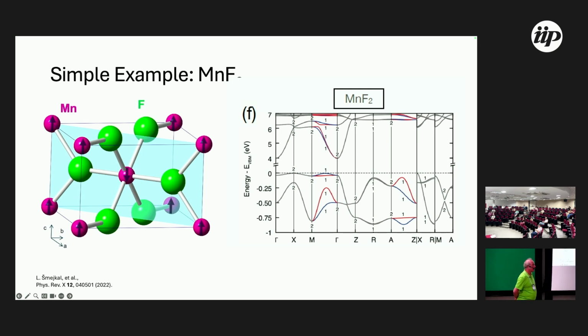That clarifies a lot. So it's basically a canted situation where you have spins oriented in different ways for different sublattices, right? Well, you have two sublattices in this case where they are pointing in opposite directions, but the immediate chemical environment is not the same. So you can tell the two sites apart from each other, just crystallographically already. But you know what I'm getting at, right?